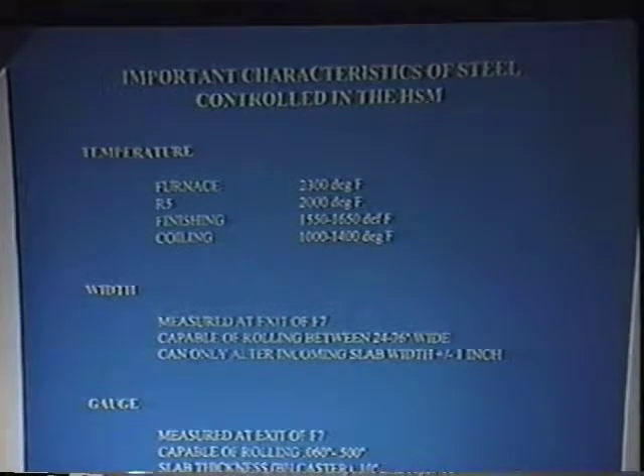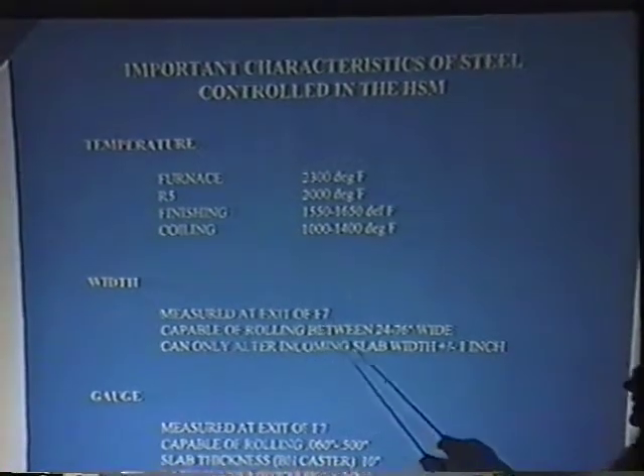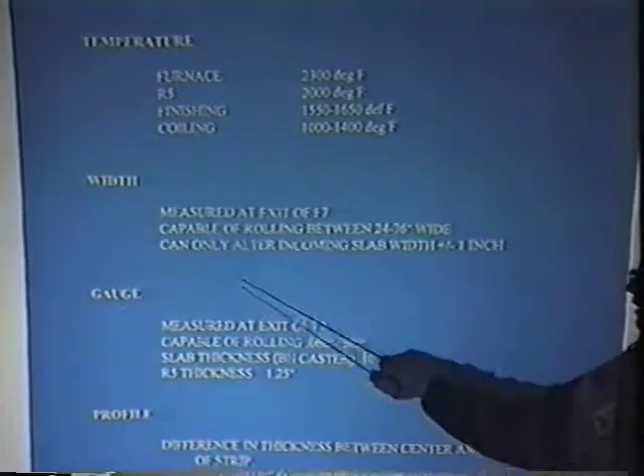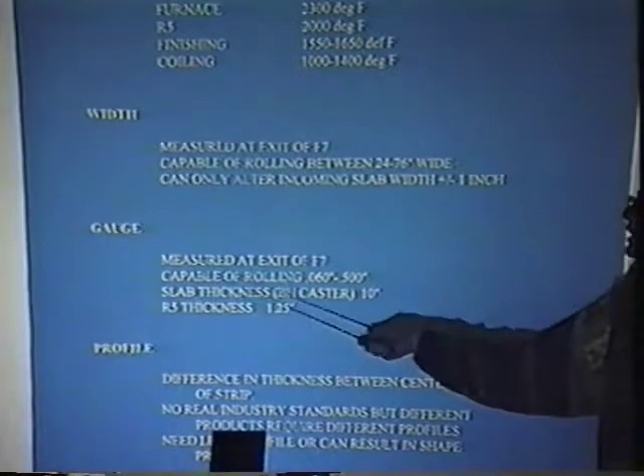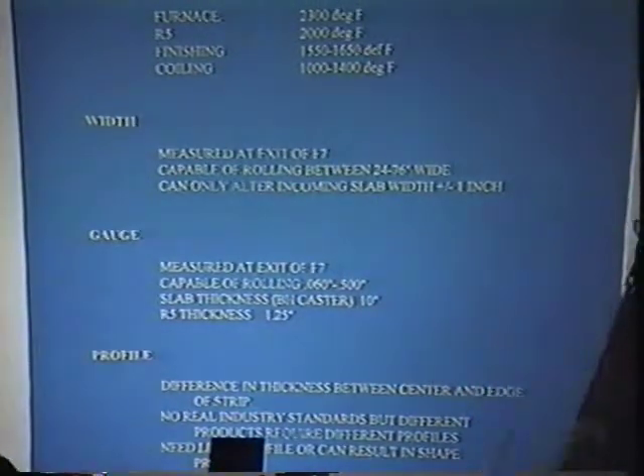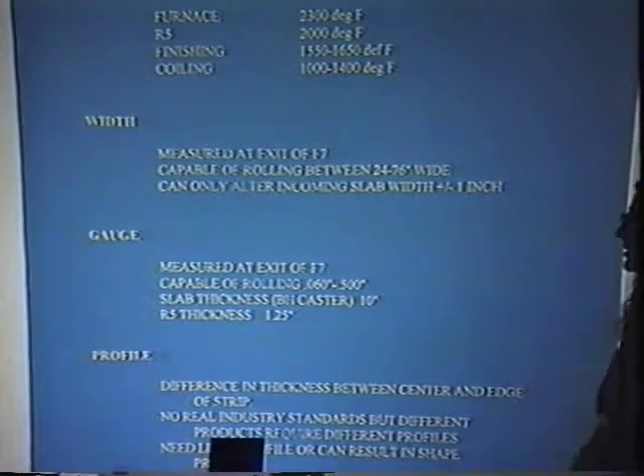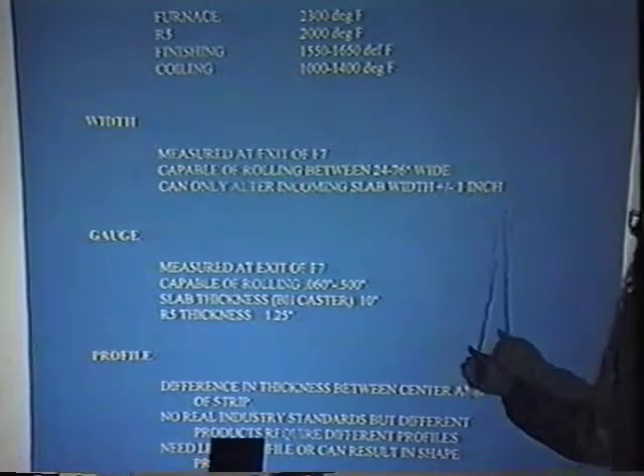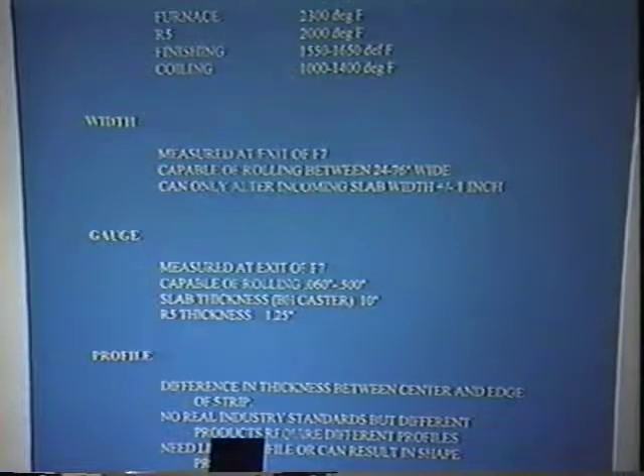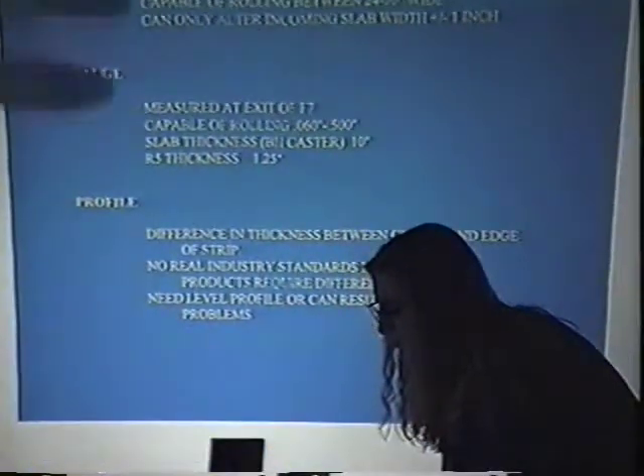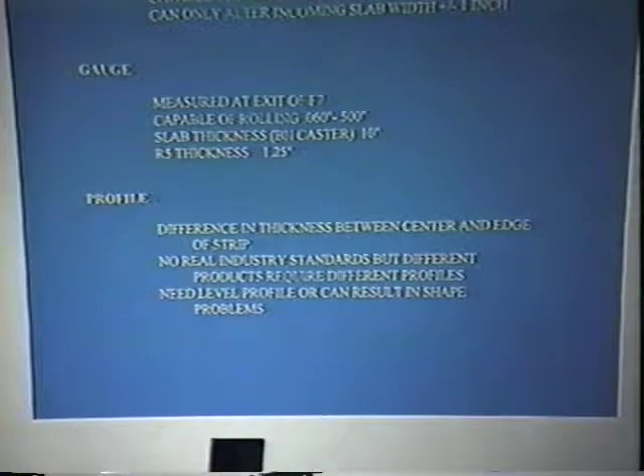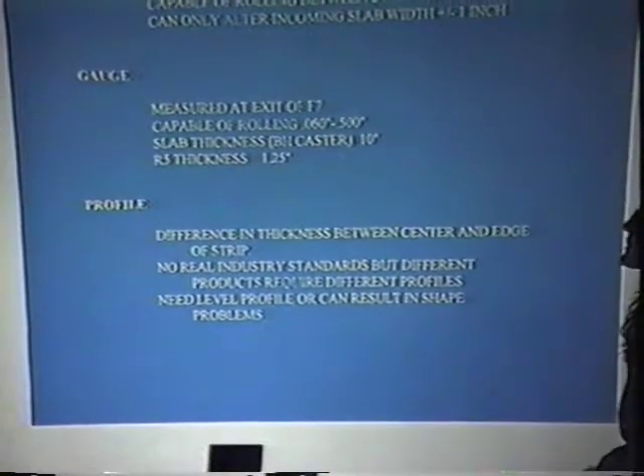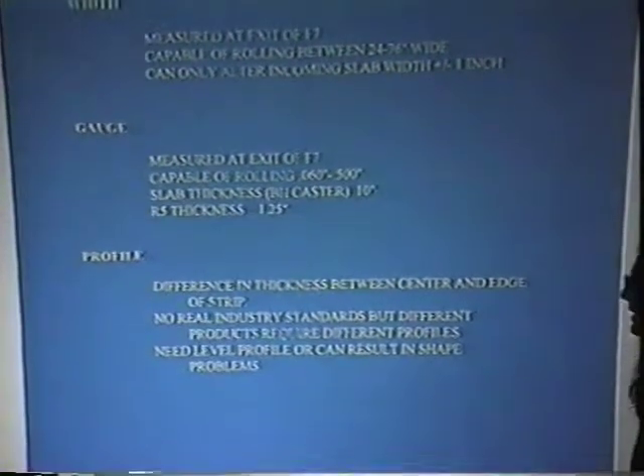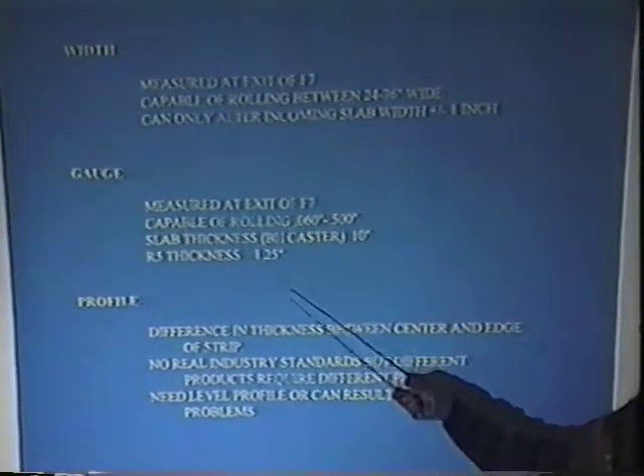The width we measure coming out of F7. That's the final width that we will report, unless it's being trimmed, and then we'll report the trim size. We're capable of rolling between 24 and 76 inches wide on an 80-inch mill. And we can alter the incoming slab width plus or minus an inch. The gauge is measured when we come out of F7. We can roll .060 to half an inch. Slab thickness out of our caster is 10 inches. And again, the thickness coming out of that last roughing stand is an inch and a quarter.